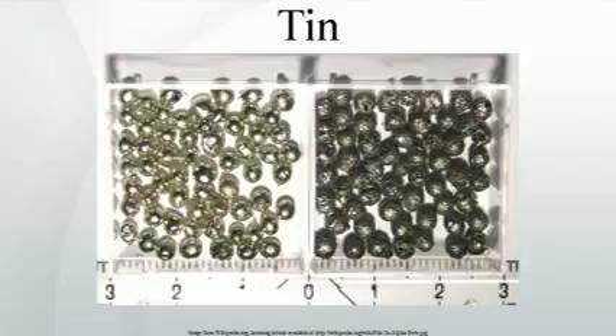PVC stabilizers. The major commercial application of organotin compounds is in the stabilization of PVC plastics. In the absence of such stabilizers, PVC would otherwise rapidly degrade under heat, light, and atmospheric oxygen, to give discolored, brittle products. Tin scavenges labile chloride ions, Cl−, which would otherwise initiate loss of HCl from the plastic material. Typical tin compounds are carboxylic acid derivatives of dibutyltin dichloride, such as the dilaurate.